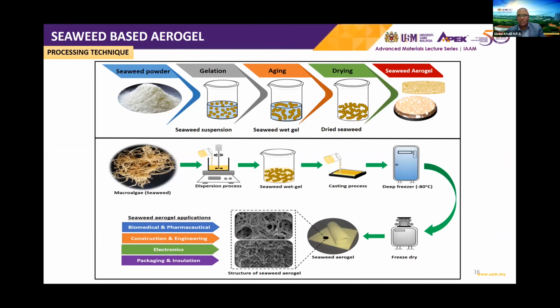This slide shows the advanced studies of the seaweed-based aerogel using seaweed as the main material. What is the aerogel? Aerogel is the porous, ultralight material consists of unique properties such as low density and high surface area. From these figures, the process of seaweed-based aerogel start with gelation process to produce the seaweed suspensions, followed by aging process to form seaweed wet gel. Then the drying process was applied using a freeze dry method at minus 80 degrees Celsius. The unique structure of high surface area of seaweed aerogel make it suitable for advanced application such as in biomedical, construction and engineering, electronics, and packaging.